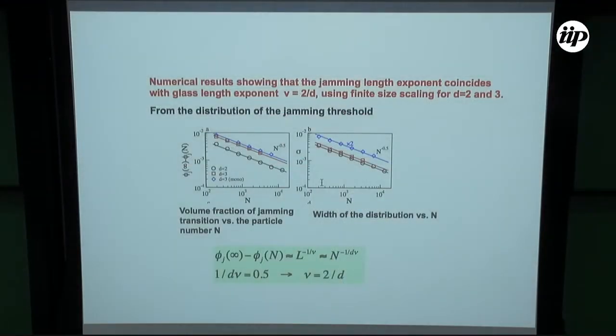And in fact, we have done numerical simulation for soft spheres at t equals 0, which is equivalent to the simulation for hard spheres, by looking at the distribution of the jamming threshold. And the distribution of the jamming threshold, in fact, is related to the exponent 1 over nu.